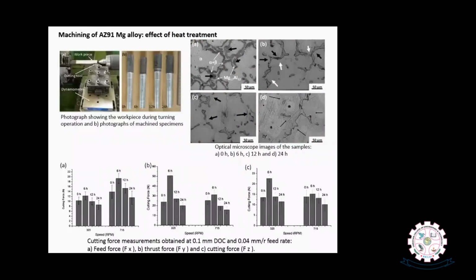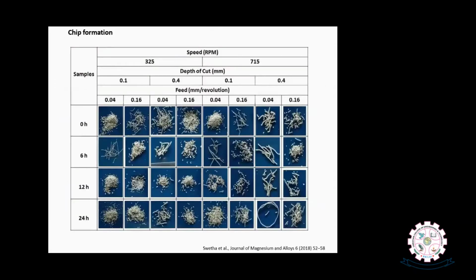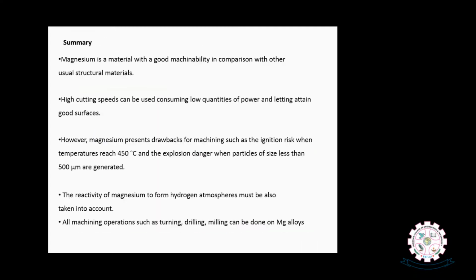This is another typical study that we have done. We altered the microstructure of AZ91 magnesium alloy by heat treatment process, and we observed that with a lower amount of intermetallic and decreased eutectic regions of alpha and beta, better machining behavior was observed, of course with increased cutting forces. The resulting chip morphologies were also studied, and a combination of morphologies was observed, with continuous chip formation and lower cutting forces for the heat treated AZ91 magnesium alloy.